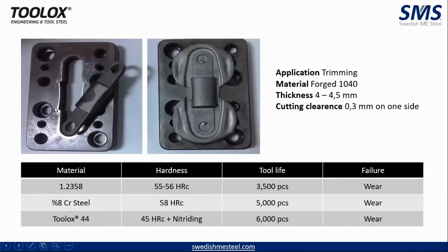This is again a trimming of forged 1040 material, the thickness being 4 to 4.5 mm. Even expensive material like 8% chrome steel has been used. Toolox 44 plus nitriding provides better tool life. The failure mechanism being the same.